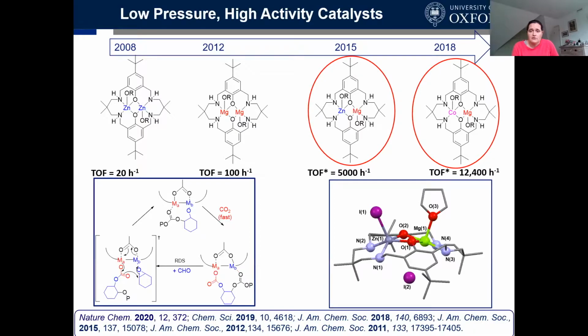It's worth saying something about the catalytic mechanism, which we've been studying now for about 10 years. Of course, a mechanism only exists as long as the kinetics substantiate it. So what we really do when we make these measurements is make lots of kinetic measurements to determine rate laws. Our rate laws have shown us that this polymerization proceeds with a fast carbon dioxide insertion and a rate determining step that involves metal carbonate attack on coordinated epoxide.